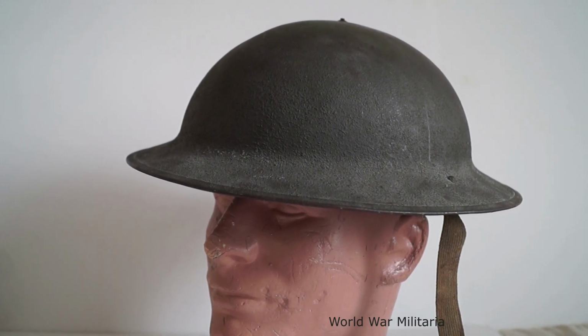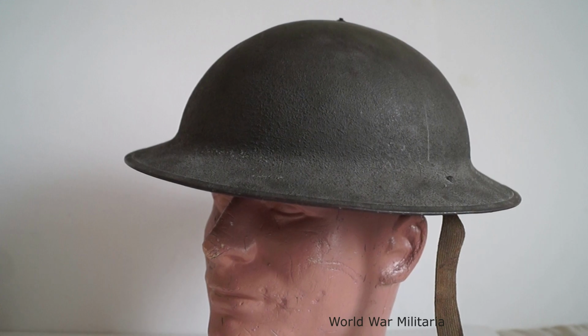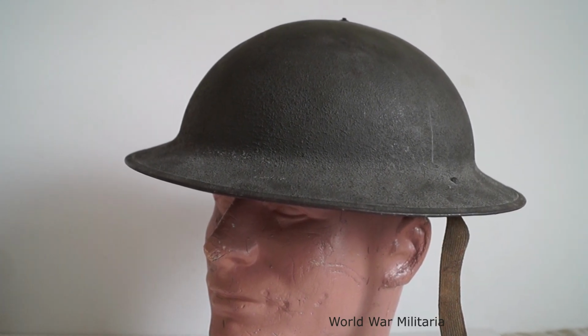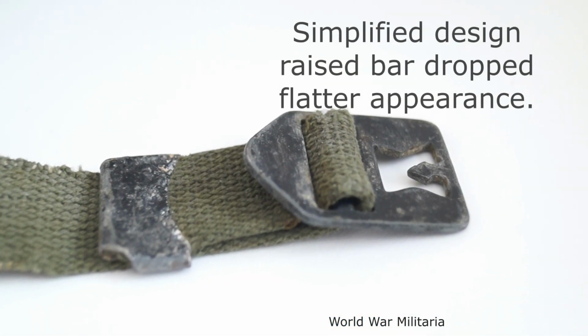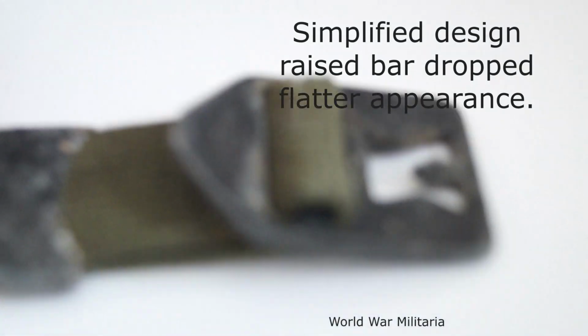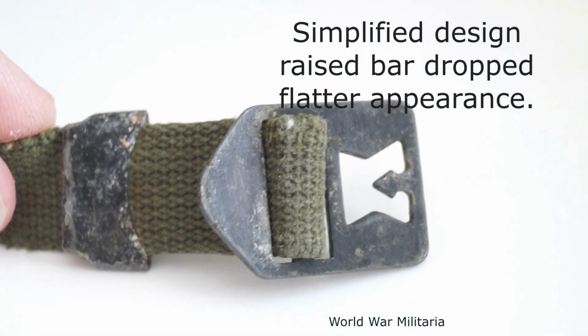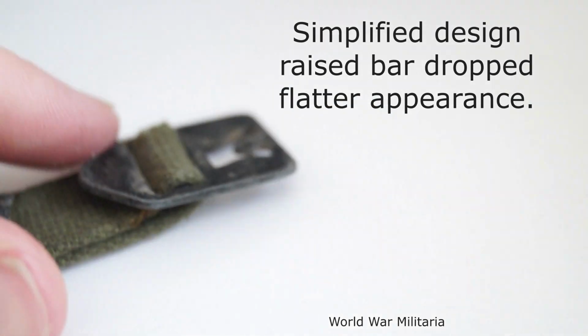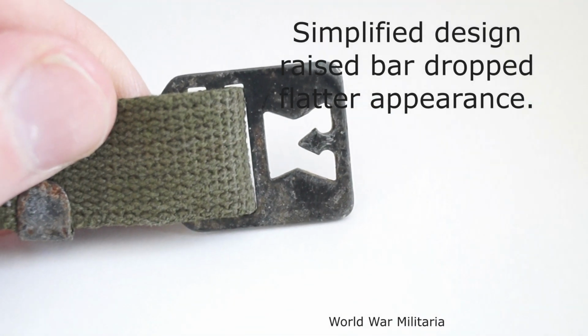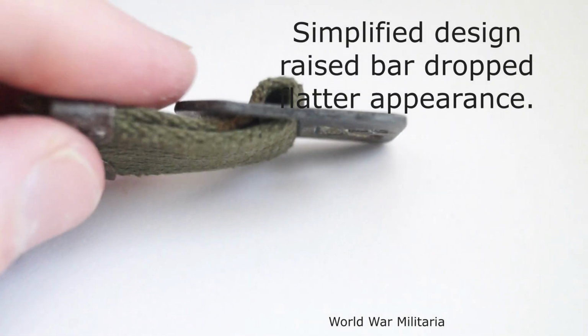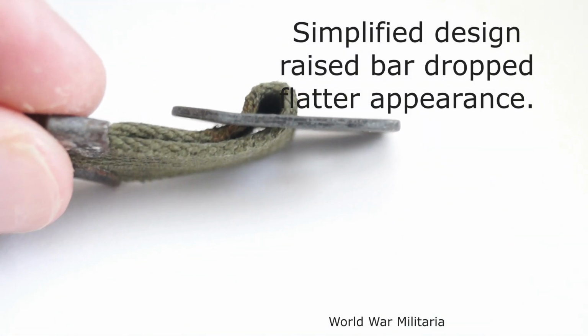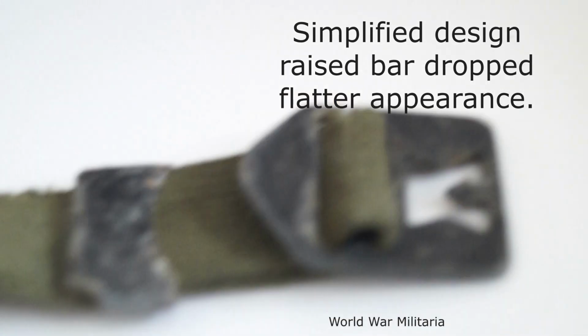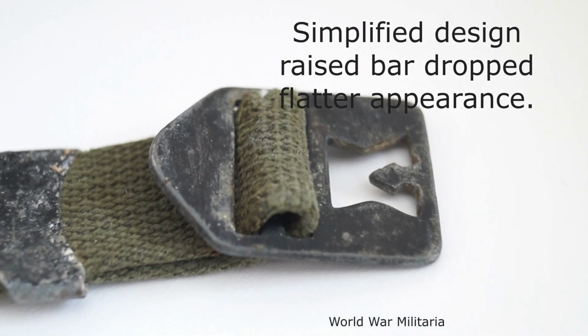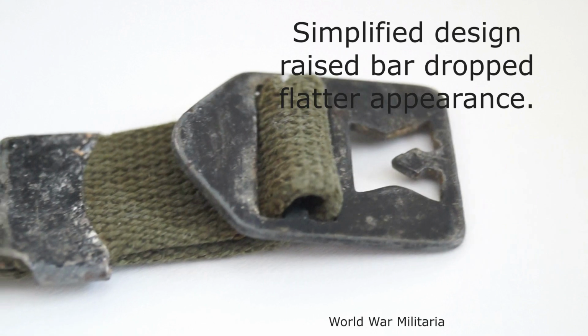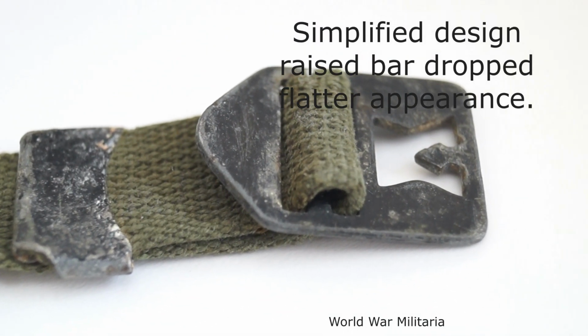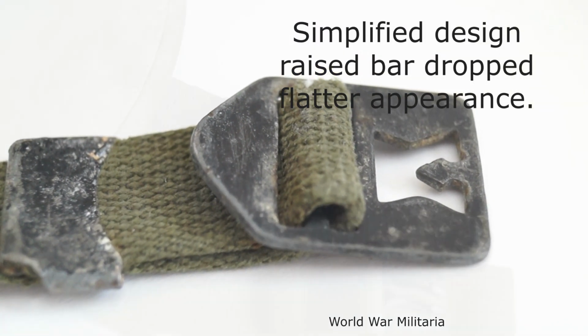corrosion. When brass became a critical material, production of the buckle, end keep and J-hook changed to steel, which was coated black. The steel raised bar buckles were made in a very limited quantity before the design of the buckle was simplified. This buckle was used on McCord steel shells exclusively. Produced circa 1943, the steel buckles suffered more from corrosion than brass buckles.